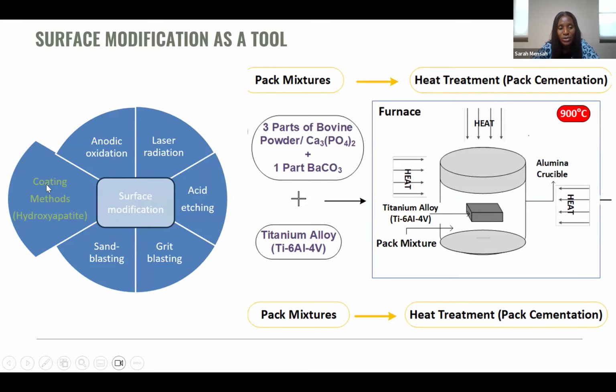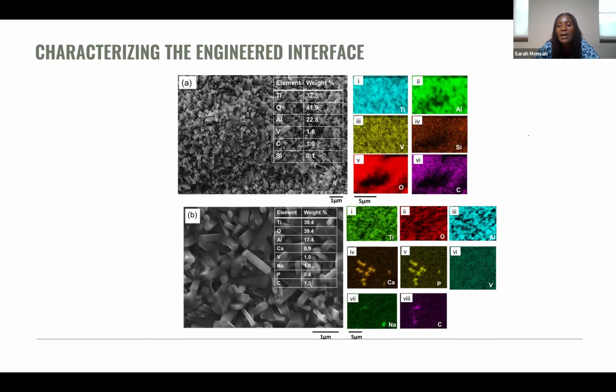One that I will zero in on is the coating method, where ceramic materials are coated onto metals to move them from being bioinert to being bioactive. One approach that I used for surface modification was coating a metallic material, titanium, with hydroxyapatite in a very simple approach. In any lab where you have a furnace, this can be done by synthesizing your hydroxyapatite. In this case, I synthesized it from bovine bone. Through some processing techniques, you're able to get hydroxyapatite and then pack it around the metallic material, then heat it to high temperatures. Through diffusion, this is going to coat this bioinert material and make it become bioactive.